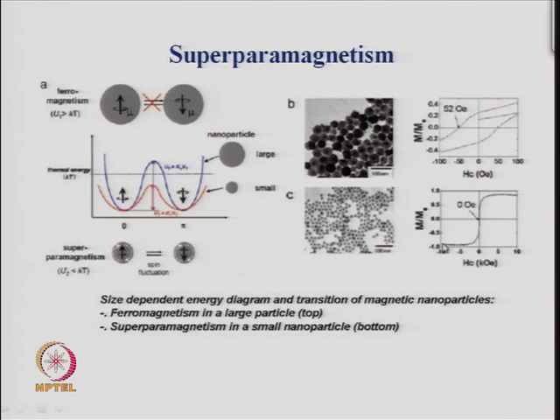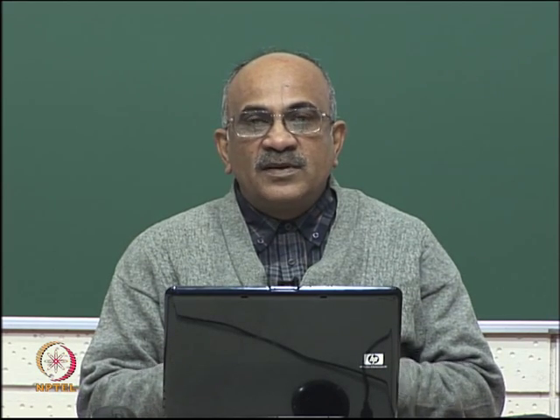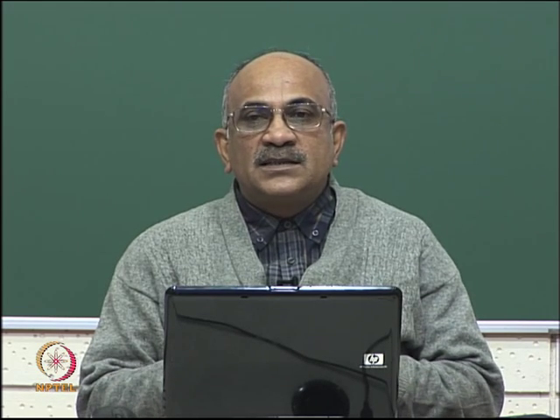So, this particular plot shows you how a superparamagnet behaves in a magnetic field, and these two plots clearly differentiate the change in the magnetic property of a magnetic material when you decrease the size of the particle. So, this is one of the most important aspects of the magnetic properties of nanostructures, the property of superparamagnetism. When you decrease the size of a magnetic material, which shows a hysteresis loop when the particle size is large, but the same material, when you lower the size of the particle to nano dimensions, does not show the hysteresis loop, but the magnetization plot versus field goes through the origin, showing no remanence and no coercive field.